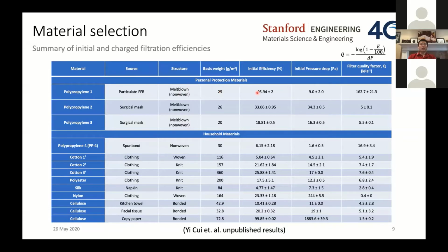25 GSM, filtration efficiency is close to about 96%. Right, this is using N95 mask materials. Its initial pressure drop under 32 liters per minute is 9 Pa. Its quality factor is very high, 163.